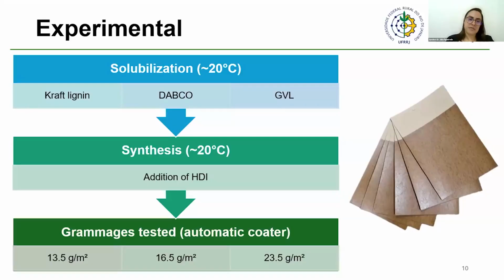So we tested 3 different grammages: 13.5, 16.5, and 23.5 grams per square meter. And we applied 2 layers. At the end of the application of the layers, we put the coated paper in an oven for 5 minutes and left it in the climate-controlled room, with control of humidity and temperature, for at least 24 hours before starting the analysis.